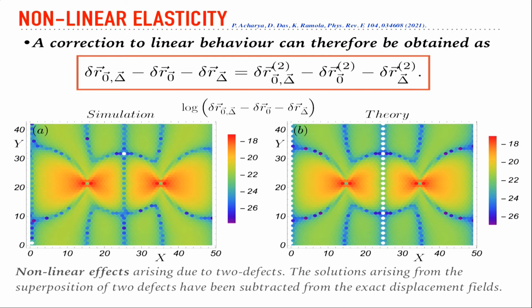And so using our second order theory, we've just numerically computed the source field at second order and then just inputted it and used the theoretical Green's function and just got this answer. And this is what we get from the numerics of using the exact sort of going to the minimum using conjugate gradient. And so this is basically exactly the same, and this is in log scale, by the way. So the correction is very, very tiny.